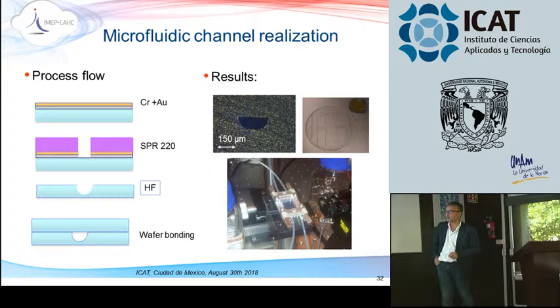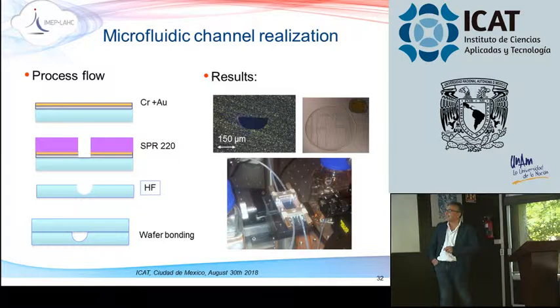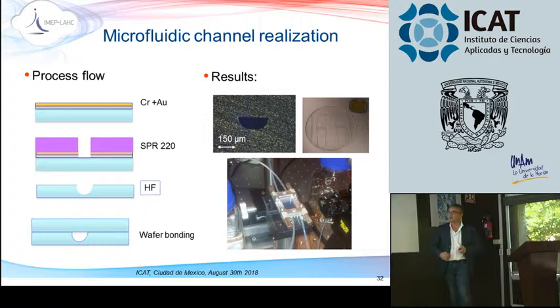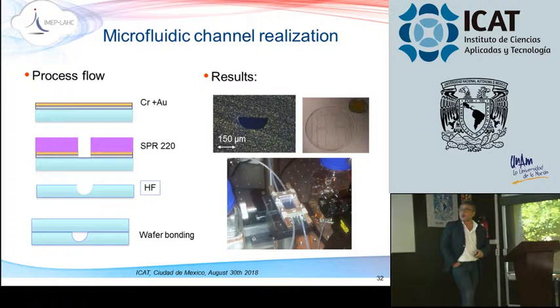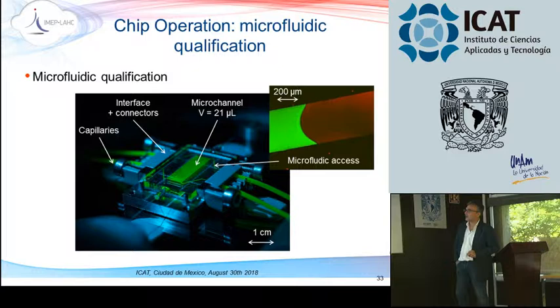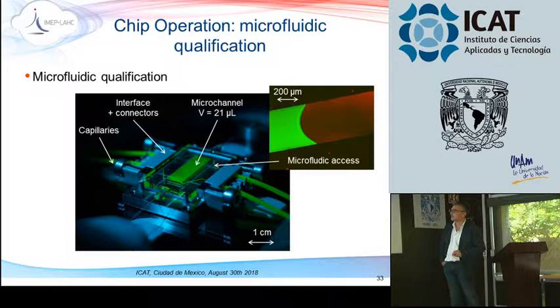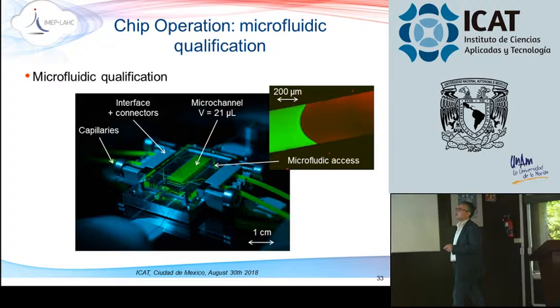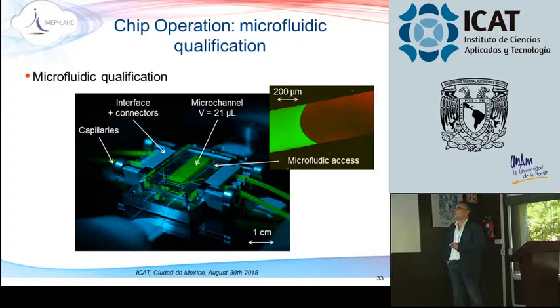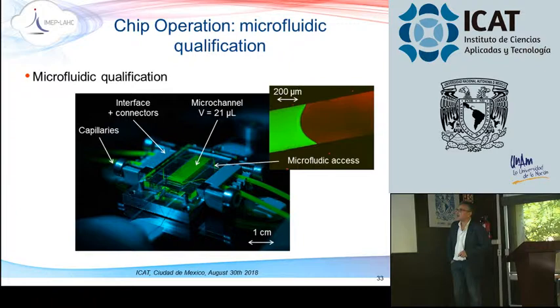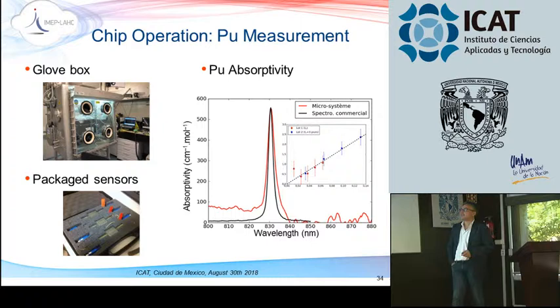You see the result at the end, you don't see any difference between the two glass wafers. You actually recreated a homogeneous material. And this is the groove that we created, this is the chip, the first interconnected microfluidic chip that was tested. So once we had the technology, we did some microfluidic characterization. So this is fluorescence, so you can see the green stuff. These are the capillaries injecting liquid. This is the part where we will sense, with a volume of 21 microliters, the connectors. You can see here the microfluidic access, and you can see the typical behavior of microfluidic channels with the tensile forces on the boundaries.